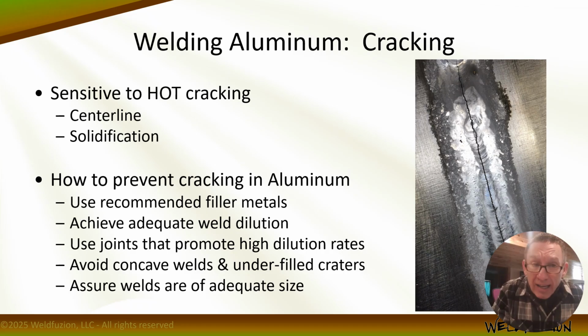Thus, to prevent cracking, we need a 4000 or 5000 series filler metal, but not 6000, because the combination of magnesium and silicon in the alloying elements would reduce strength and cracking would likely occur. Right? So manufacturers provide charts that recommend filler metal alloys for specific base metal combinations according to the intended service requirements. Those charts should be followed as a starting point for procedure development to make sure we have compatible alloys that are known to make acceptable welds.